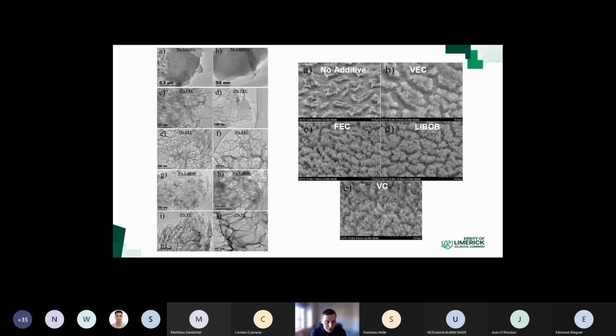Okay, when we looked at the actual material after cycling in each of these electrolytes, we noted that for VC, the best performing one, we did get this morphology transformation again. And actually for the 3 best performing ones, we did get that morphology transformation, and you can see that ligament type structure forming again. For VEC, we did get it as well, but we also found these amorphous areas that did not have that ligament type structure. When we used no additive at all, the ligament structure did not form. And that clearly showed why the no additive doesn't retain much capacity at all. It's because you're not evolving into a stable morphology.